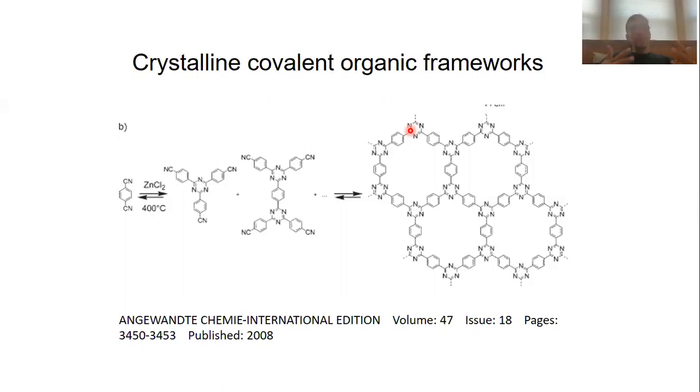Okay, so on a sheet of paper, you could very easily imagine that this chemistry would extend to many other structures. For instance, we could replace this phenylene unit here just by a diphenylene unit and do exactly the same reaction. And in principle, the same reaction works, but it has been found that whatever conditions you try, the stuff doesn't crystallize.